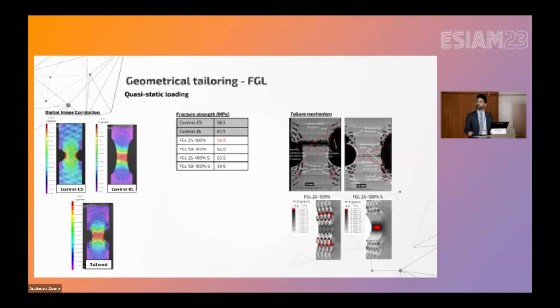Let's see what the effect is on mechanical properties. Of course, the goal was not static loading. We just wanted to see if it gets any worse in static. But we could see that in almost all cases, the failure load was increased. Then we look at the broken specimens.